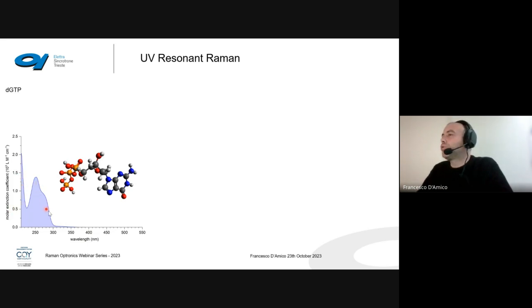This is the absorption spectrum of dGTP. It means that most of the electronic transitions are below 300 nanometers. In particular, here we have two peaks in absorption, then we have a valley, and then we have a new increase in the absorption going to higher energies. What occurs? Let's see what occurs when we collect the Raman spectrum.